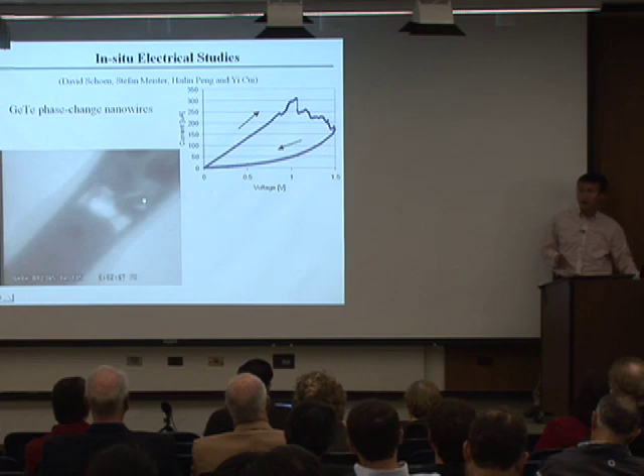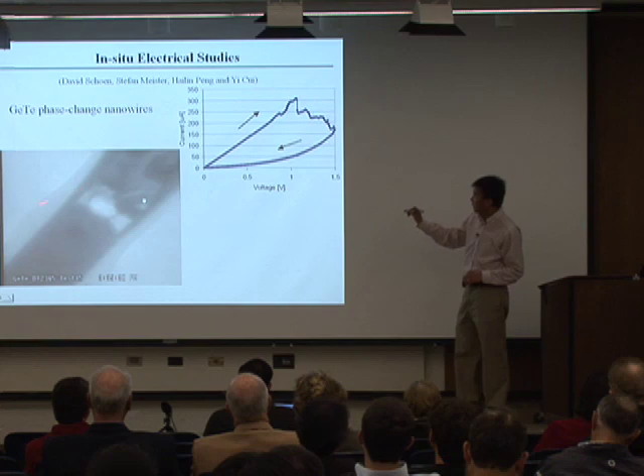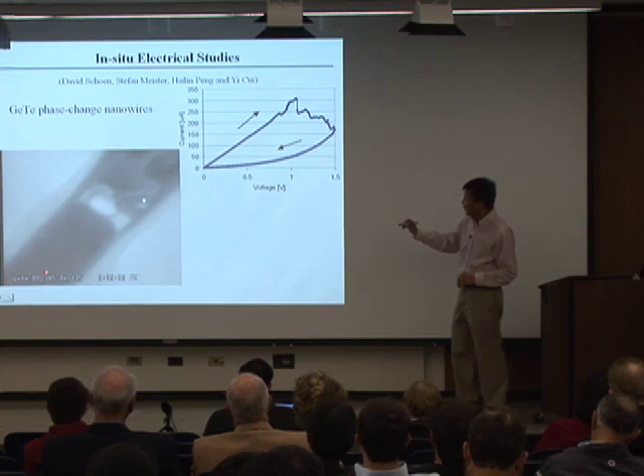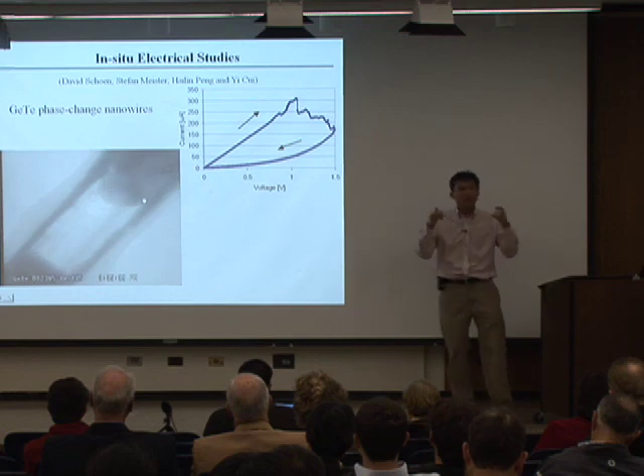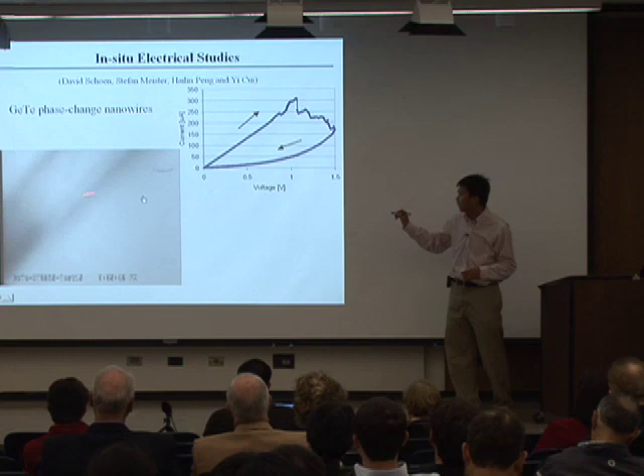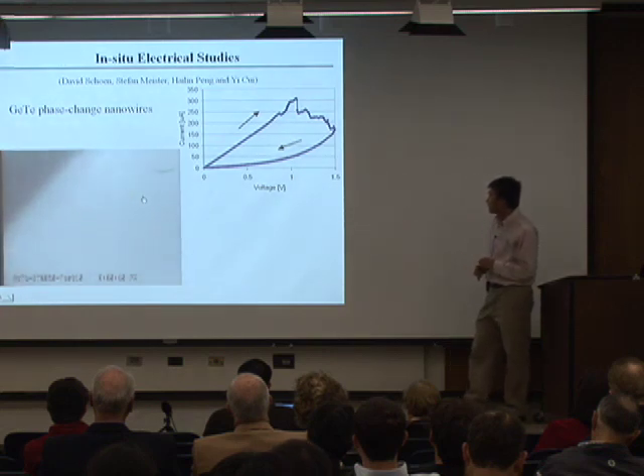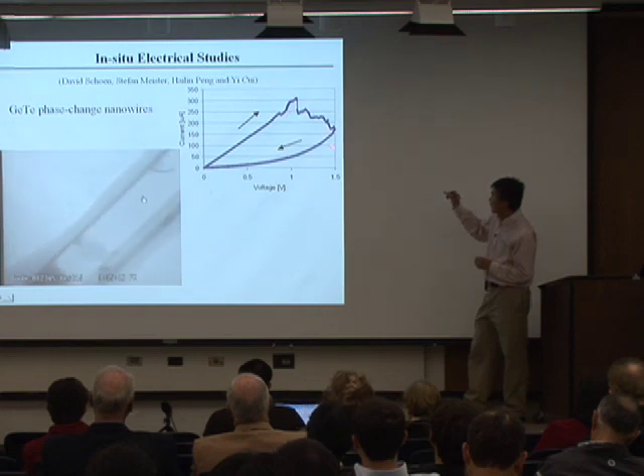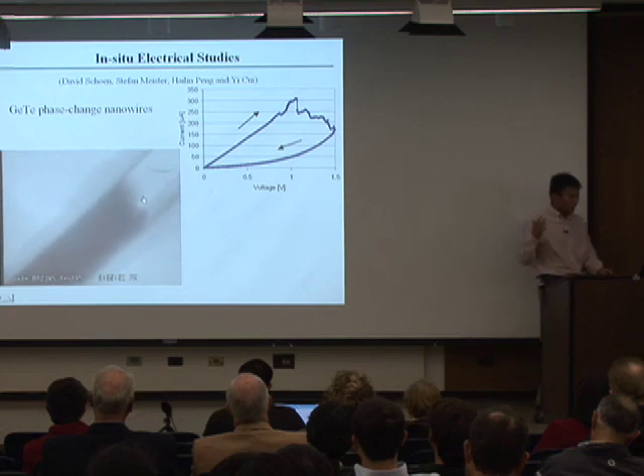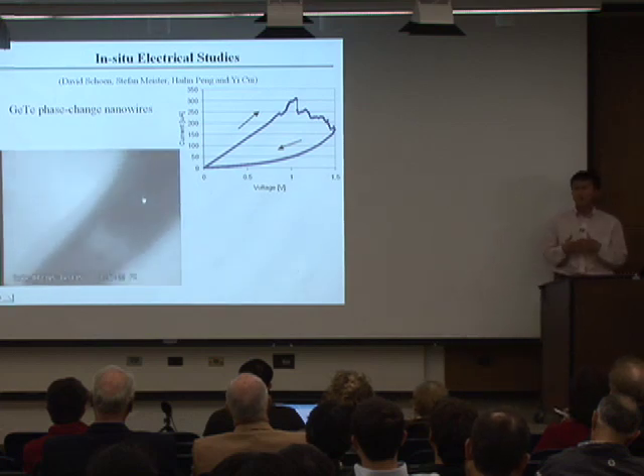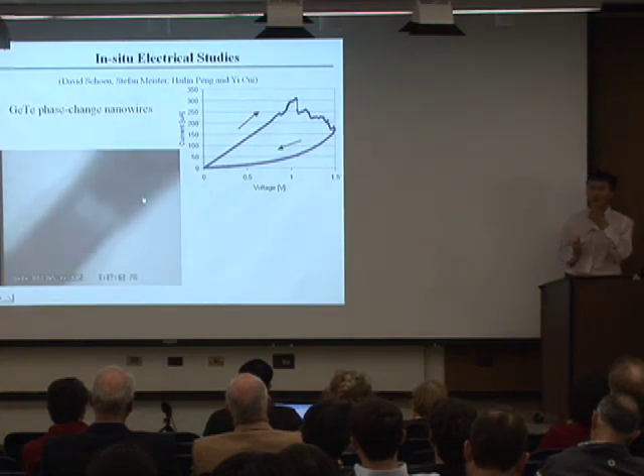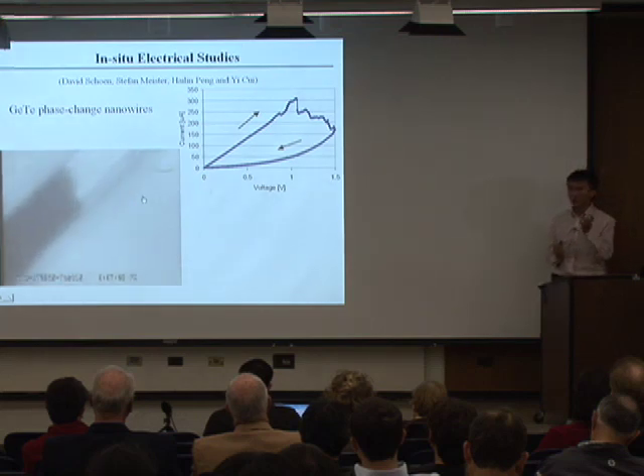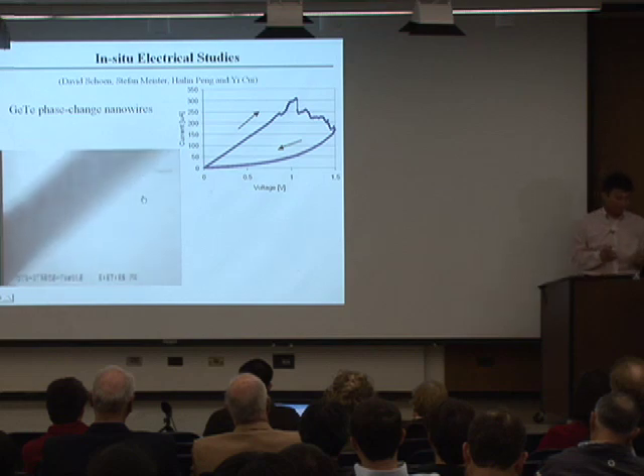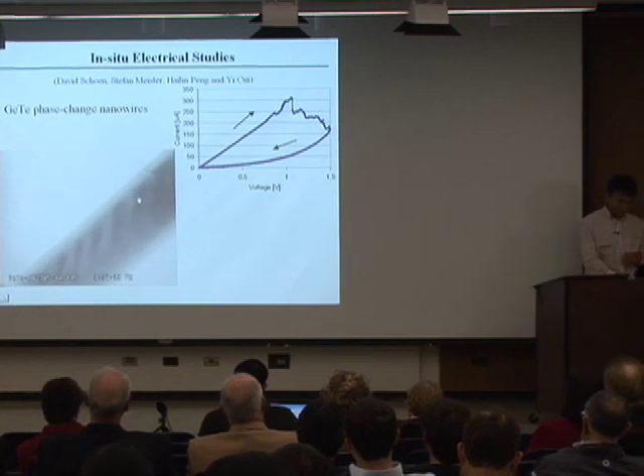Well, a lot of other things happen other than crystalline and amorphous transformation. So this is a nanowire encapsulated by layers. Now it passes current through it, it's going to melt. Size is about 100, 200 nanometer or so. You start to see materials moving around like crazy, forming this nanotube structure. It's hollow. So you see this IV curve, current really goes like crazy. So we hope to use this similar type of technique to do our silicon nanowire battery measurement and also other materials battery measurement, allow you to watch this in real time and really understand and also control your materials property better.